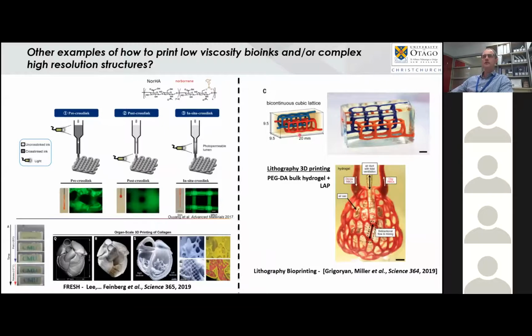I'm just going to skip ahead. I think there's a broad range of other exciting techniques for being able to cross-link low viscosity bioinks or really complex structures. So the Burdick group looked at a number of different ways of in situ cross-linking. There's obviously the FRESH technique pioneered by the Feinberg group, which allows you to print very low viscosity bioinks in a suspension bath, which you can then release over a period of time to print really large scale constructs, which are essentially self-supporting and have significant capability to, like I say, print very, very large clinically relevant size features.